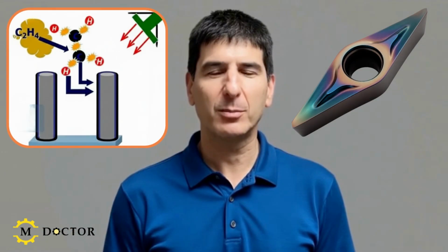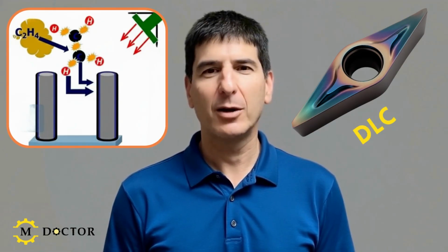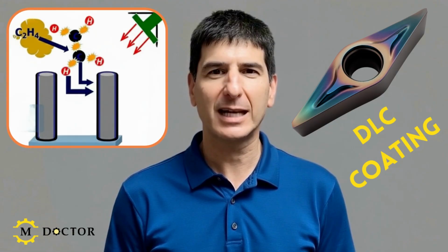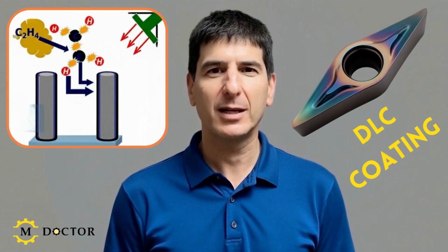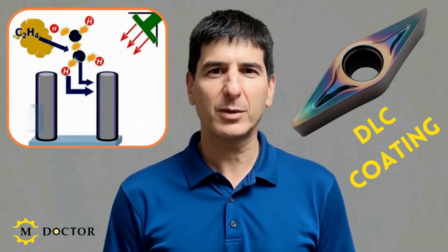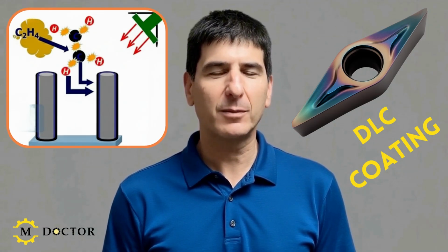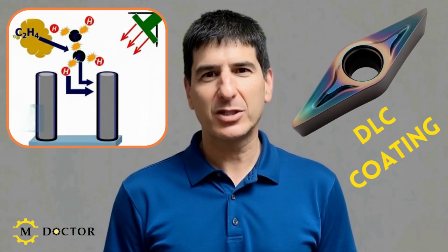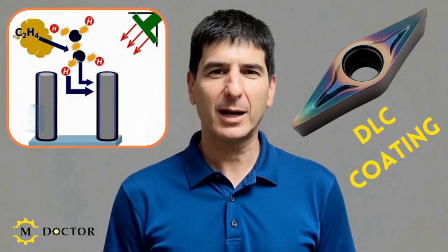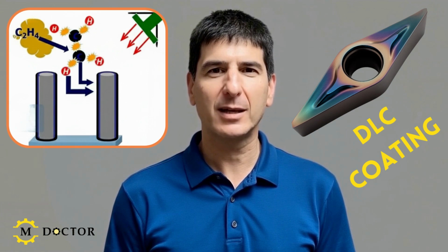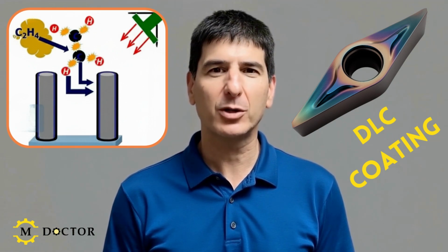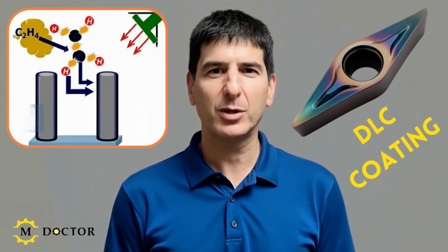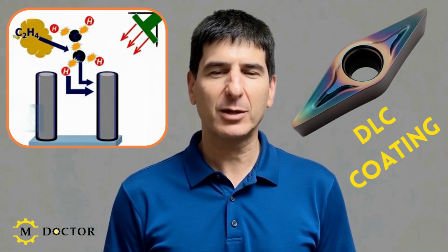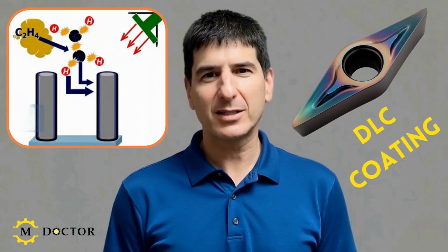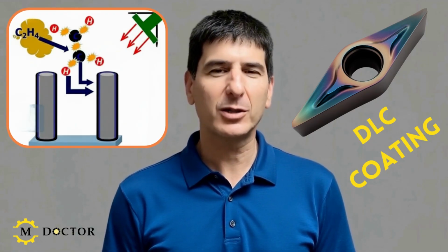A mid-range solution between PCD and carbide is DLC coating. DLC stands for diamond-like carbon. It is a specialized surface coating, made from a nanocomposite of carbon and hydrogen. Applied through PVD or CVD processes, it exhibits diamond-like properties including high hardness, excellent wear resistance, and chemical inertness. It can serve as a more affordable alternative to PCD for aluminum machining. While PCD remains superior, DLC provides some of those advantages at a fraction of the cost.